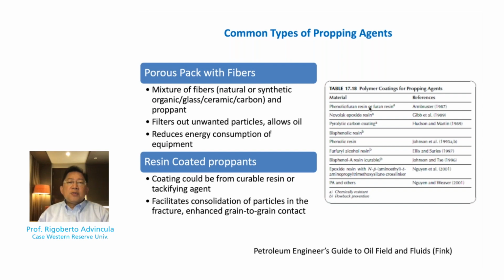This has been very useful in that the main idea, as I said, is to prevent closure stresses in the fracture and keep it open as much as possible. Now, emphasizing resin-coated proppants, the game-changing part there is the polymer coating that is used to coat the proppants. In other words, we can take sand and coat it with phenolic resins, Novolac type of resins. And by the way, the phenol formaldehyde or phenolic resin is the most common type of thermoset resin coating on proppants. So the idea is to improve the crush resistance of these proppants by armorizing, or putting a thermoset shell of a polymer around these materials.